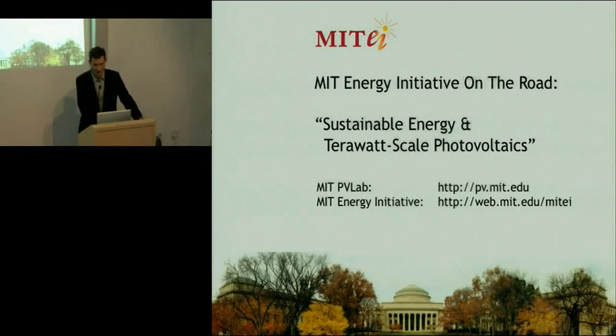While certainly there's efforts in these directions, one usually does that once one already has an established solar cell material. So the first step is to get a solar cell material that works with some band gap. And then from there you can innovate and alloy and change the band gap properties. So we're one step behind that still in terms of the earth-abundant compounds. In terms of the non-earth-abundant compounds, they're already quite there. With the III-V compounds, certainly indium nitride, indium gallium nitride, and other compounds, you can alloy in this way.